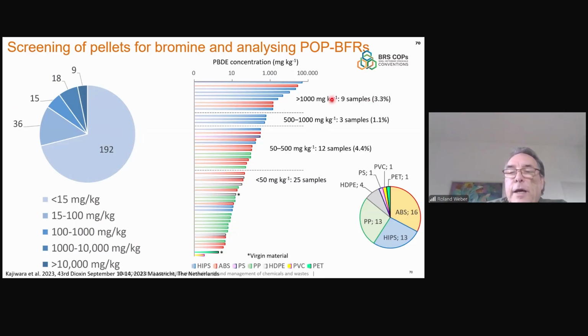So there we found that 9 samples had PBDE concentrations above 1000 milligram per kilogram. Further 3 samples were above 500 milligram per kilogram. And 12 samples further were between 50 and 500 milligram, and then 25 samples were between 15 and 50 milligram per kilogram. What you also see with the colors is that basically only high impact polystyrene and the ABS plastic were above the 500 milligram per kilogram. So you see also here that some flame retardants were very specific in the application of the different polymers. Also for this, it would be nice to have more such detailed studies.